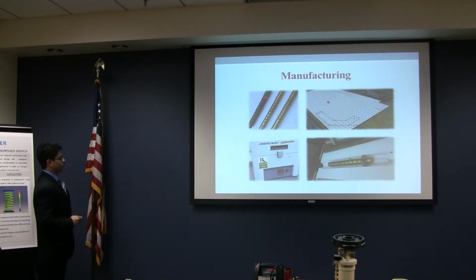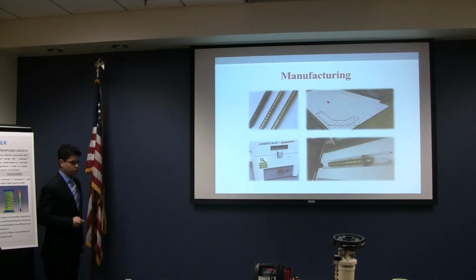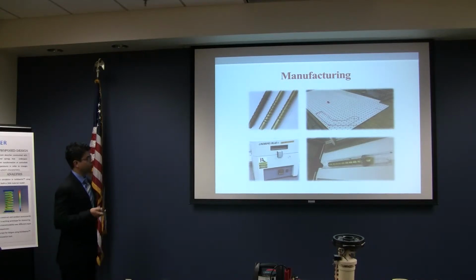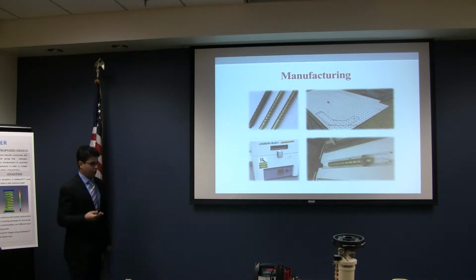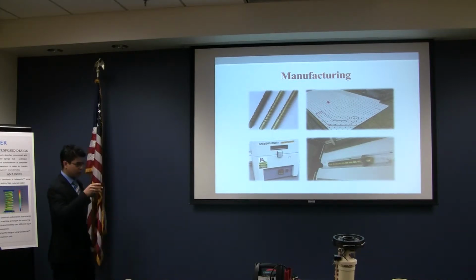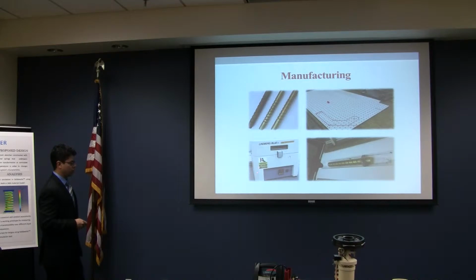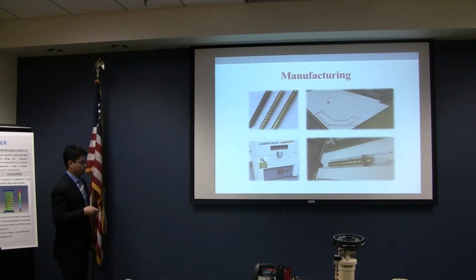So the manufacturing was making the springs. Next, the fixture. The fixture was made using wood, and we got perforated wood so we could pass the little stick through, so we could make a truss. We used the oven to heat treat the material, and this shows how we did it. We crimped the wire to the ends, and then we processed it with the heat treatment.